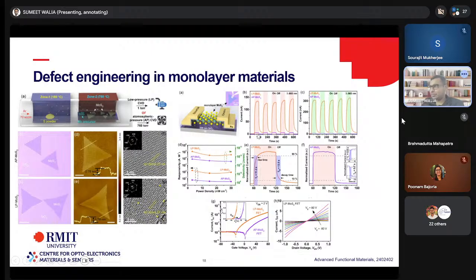In the light detection domain, when we compare that, what you see is when you have more sulfur vacancies, now these defects essentially trap carriers, so it increases the recombination lifetime, so you get a much higher level of photocurrent. However, if you compare it to the oxygen passivated one, the difference is, the oxygen passivated MoS2 tends to have a lower photocurrent magnitude, but faster rise and fall times. So the message here is that by controlling the amount of oxygen during synthesis, you can create both electrical and optical signatures that you require. If you want slower decay, for example, in neuromorphics, you can engineer more oxygen vacancies in the system.